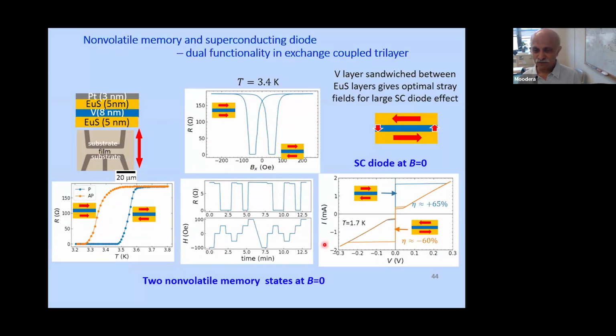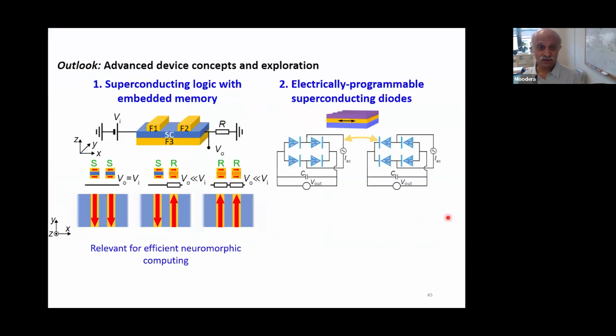And on the right side, what I want to specifically show is that we can use the same kind of architecture. You can either have memory or you can have the diode. It just depends on what temperature you operate at. For example, at a little bit higher temperature, somewhere in the middle here, you can have this behavior. When you go to low enough temperature, by toggling the magnetization, you can have either a completely superconducting state or a resistive state. So this allows us to have a superconducting diode in zero magnetic field. Efficiency is very good. So this is all advantage.